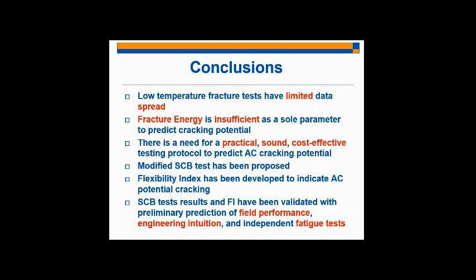This motivates a need for a practical, sound, and cost-effective testing protocol that would allow us to predict our AC cracking potential. To address this need, we've modified the SCB test. We've modified how we look at the results from the SCB test. We proposed this new approach of looking at the load displacement curves, extracting critical geometric properties: the fracture energy and the slope of the line fit to the first inflection point past the peak load.